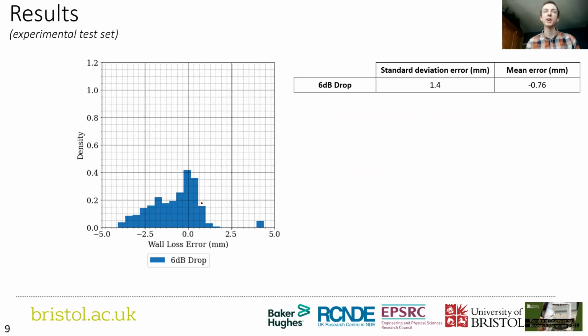We've got an error histogram here. We love all our errors to be at 0. And this is the experimental test set. But even though I'm only sizing defects from 1 to 5 mm in size, I've got a standard deviation of 1.4 mm here. So we've got some massively undersized defects. And in fact, most of them are sized pretty inaccurately.